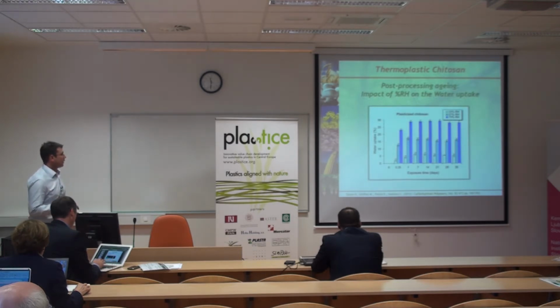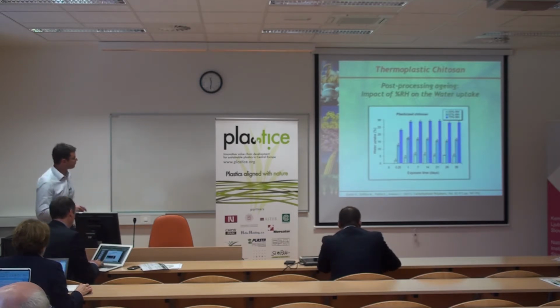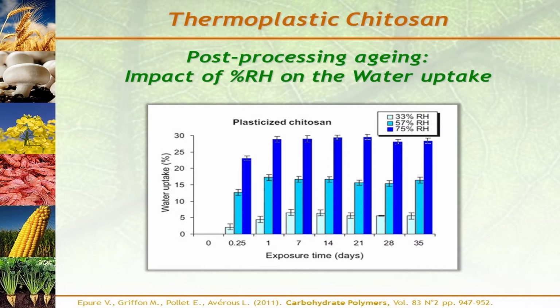As you may see here, the storage time and the relative humidity atmosphere at which you make this post-processing aging of the plasticized chitosan may vary with the relative humidity. And here is the water uptake with time. And you see at 57%, 75% relative humidity, you have a fast increase in the water uptake, and then it's more or less constant after 1 week. And the same trends with a lower water uptake for lower relative humidity atmosphere. But you see very important differences in the water content of the material after 1 week, one month. So this will affect strongly the mechanical properties of the thermoplastic chitosan.